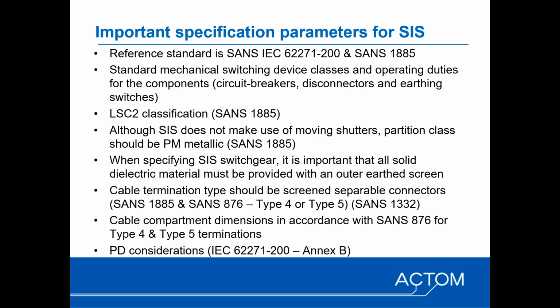While the flexibility is provided by a type 4 outer cone separable screen connector, or screen separable connector, it is very convenient in terms of being able to plug cables back to back onto one another to accommodate multiple cables per phase. One has to be very sure that you provide proper cable support because of the mechanical strain that could be placed on the outer cone bushing.